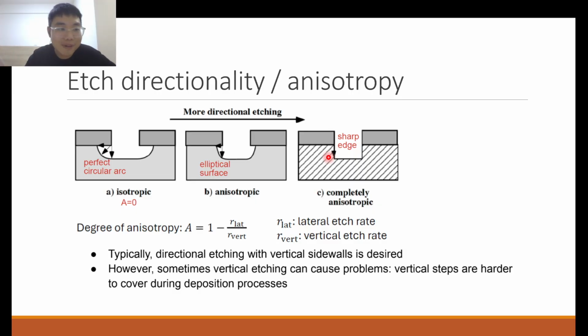Okay. So you may think the directional etching is good, because you etch straight where you want it to etch. You don't go left, right, wherever. However, sometimes you want it not completely anisotropic. Why? Because if we do the vertical etching, we have sharp corners like this. What's the problem with sharp corners like this? When you do the next step, you may not be able to get a good coverage. So maybe you want a more curved profile sometimes. Sometimes you want a more slanted profile. It may be better for subsequent processing steps. That's something you have to consider.